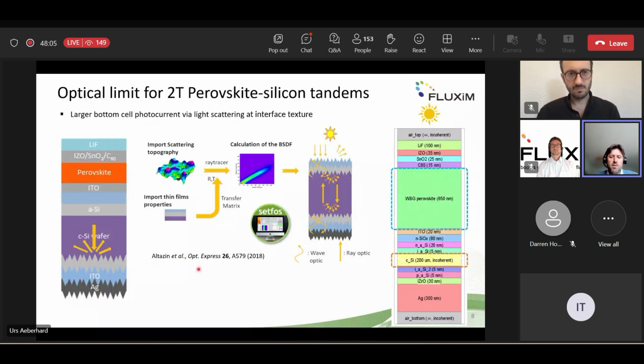We model this in our software, which is called Setfos, using a validated multi-scale approach. So first, you compute the properties of the thin film part, the coherent stack, as we call it. In this case, it's the coherent stack here on the rear side, on top of this texture. And this then is used in a ray tracer to compute the scattering properties of the complex interface. And this again is used in the transfer matrix type retardation model as before. So you have then just the propagation again in the entire stack, but including the scattering at the interface.